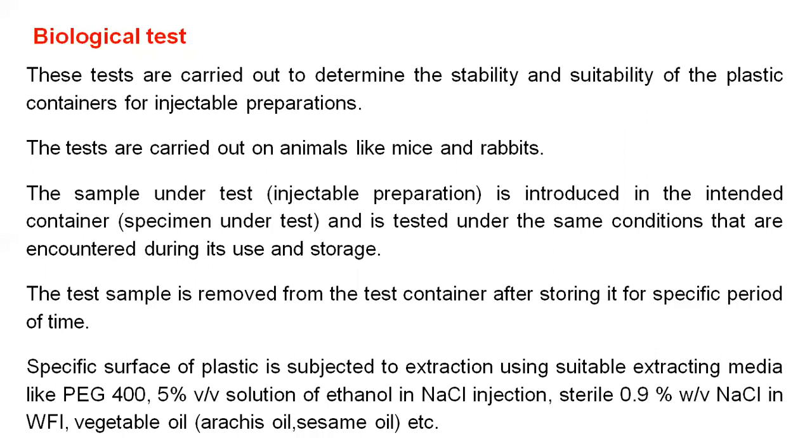Specific surface of plastic is subjected to extraction using suitable extracting media like PEG 400, 5% volume by volume solution of ethanol in NaCl injection, sterile 0.9% weight by volume NaCl in water for injection, vegetable oil such as arachis oil, sesame oil, etc.